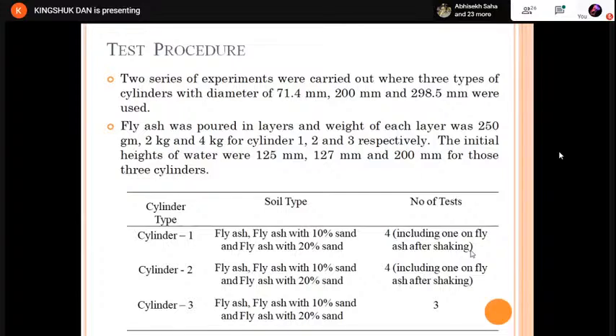Now, how is it done? Suppose for cylinder 1, the first layer of fly ash is poured. At first, there is a water height, for cylinder 1 it is 125 millimeter. Then the first layer of fly ash is poured, which is about 250 gram. Then it is allowed to settle. After some time, it begins to settle, and a clear interface is shown. If we draw the time settlement curve, it is very visible that it takes nearly 4 hours to settle completely. That means full settlement is there after 4 hours. So we allow it to settle for 4 hours.